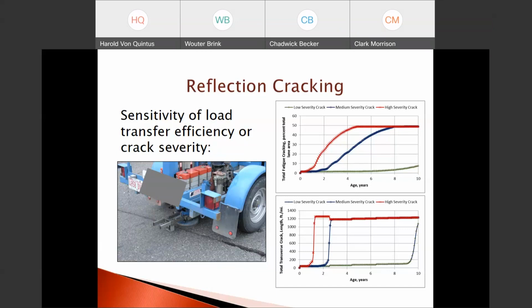The bottom graph shows the same thing, but for transverse reflective cracks. The red cross is high severity transverse cracks. The blue circle, medium severity transverse cracks, and the plus green line is for low transverse crack severity in terms of predicted transverse reflection cracks from the existing pavement.